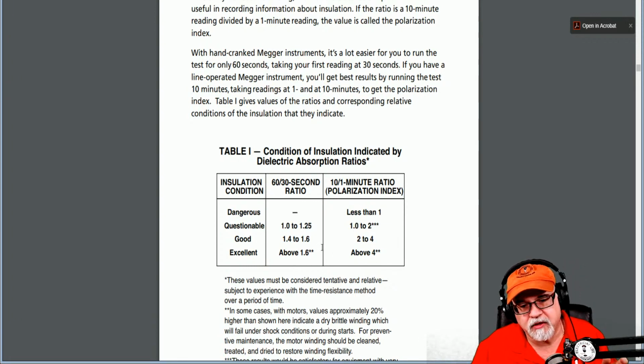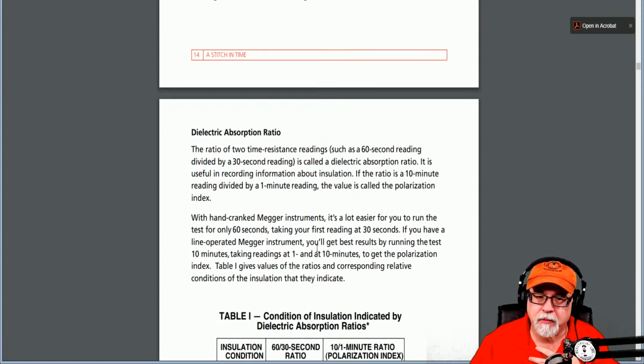Now, that brings me to this. So I've kind of told you all the tests. We recommend the 10 and 1, but I would prefer you to do a test: take a reading at 30 seconds, 1 minute, 5 minutes, and 10 minutes. So basically, you're just doing a 10-minute test. That's the best. Dedicate 10 minutes to this test, okay? Don't be in such a hurry.